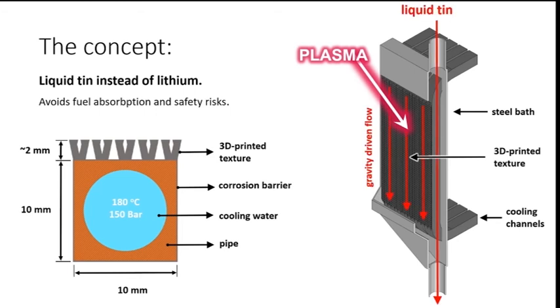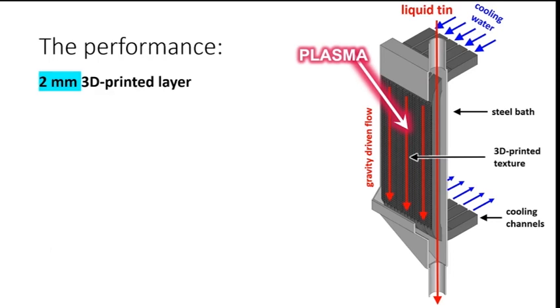We inject liquid tin from the top, and gravity is just slowly going to drive that to the bottom. Very, very slowly, actually, because there is a little bit of viscous drag, but also there is magnetic drag, which is very significant because of the high magnetic field. And then there is the coolant going through the pipes. That is roughly the layout. All right, so we've set these parameters, and now we can assess: did we do our job? That is the question.